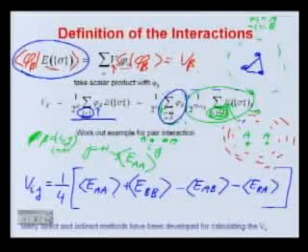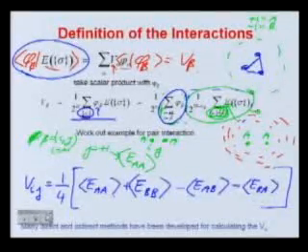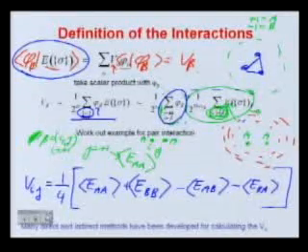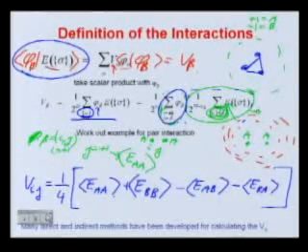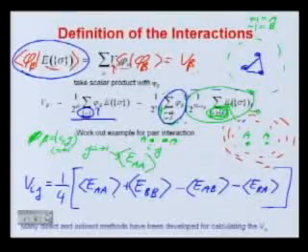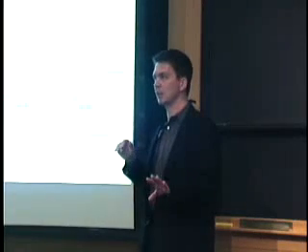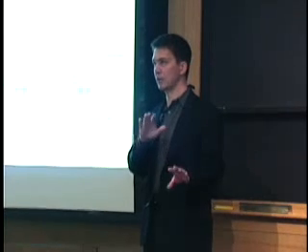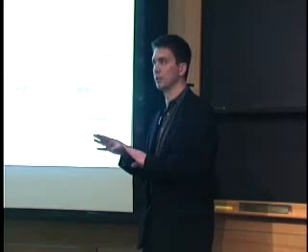The other thing is that indirect effects can be included. If you truncate your lattice model at pair terms, because it's an infinite expansion and at some point you'll have to truncate it, you are still including many body quantum mechanical effects, because they enter in the calculation of the energy of these. So what you should understand is that the level at which you truncate the cluster expansion, the lattice Hamiltonian, has no correspondence to the level of physics for, say, your electron physics.